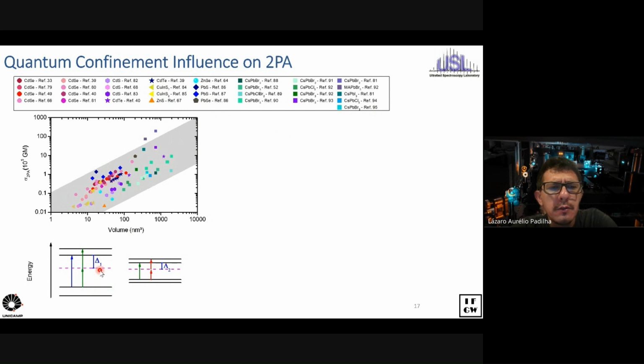So if you have a material that has a smaller band gap, even though the detuning appears here, this delta 2 will obviously be smaller than this delta 1. And if you run the calculation, you're going to see that this influences the two-photon absorption, because if you remember the equation, this term appears in the denominator. So if you run the calculations, you realize that the two-photon absorption cross-section, or the two-photon absorption coefficient for bulk semiconductors, should go with 1 over the band gap to the cubic. And if you do the same for quantum dots, you basically see the same dependence on the material band gap. And the reason is basically this intermediate state resonance down here.